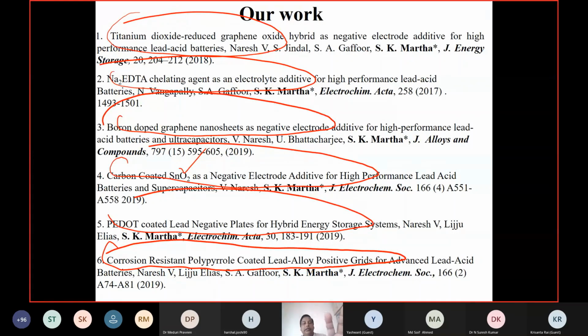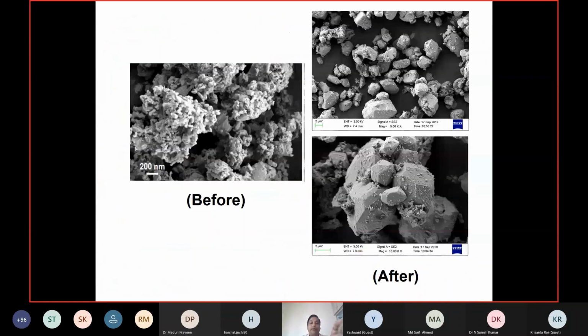The thesis was the development of high performance lead acid battery through electrode and electrolyte additives. Still a lot of work is required to improve the performance of lead acid battery. So sulfate is a major issue in lead acid battery. I told you nanomaterials become, you see here, micro. This has become 5 or 10 micron. Even if it is a 50 nanometer particle, in real it becomes several micrometers.